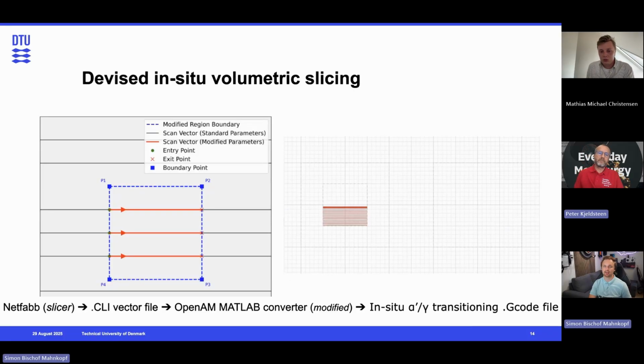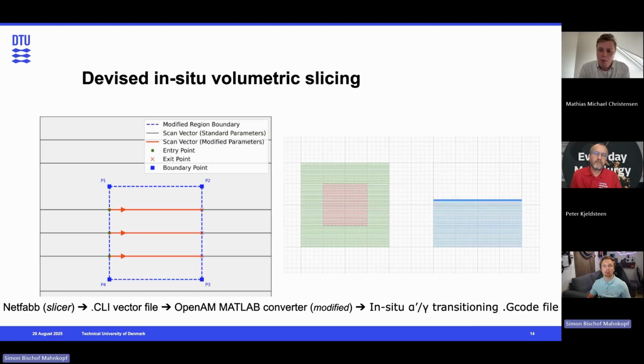Yeah. But what we then did is we tried to find a way of avoiding, as Matthias mentioned, the edge effects where you print one object with edge defects and then try and start a new scan line, you will always have defects. They tried to overlap them to get some remelting, but you still saw some porosities. So what we did is we didn't slice it as two different objects. We sliced it as one, and then we defined a region where we modified the parameters. As I've shown here on screen, we defined a boundary geometry. And whenever a scan line would cross that boundary, it would then get this ramping of either the power or scan speed or duty cycle. And it led to an effect as shown in the second picture, where there's a single scan line going through everything instead of being split up to avoid edge effects.